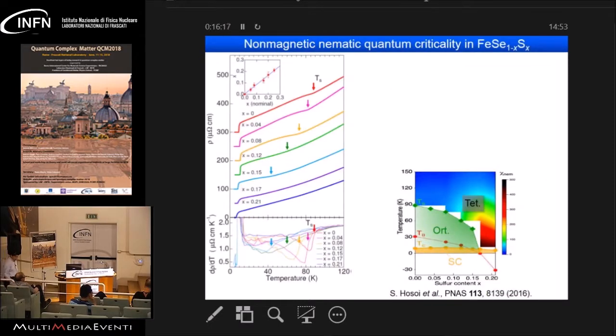So we want to look into this problem further, and we want to look at this system. This is iron, selenium, sulfur. So we substitute selenium with the isoelectronic sulfur like this. So this is a set of temperature dependence of resistivity data. And as you can see, we can assign this nematic phase transition as a kink. And we can construct a phase diagram like this. And the nematic phase transition temperature goes down.